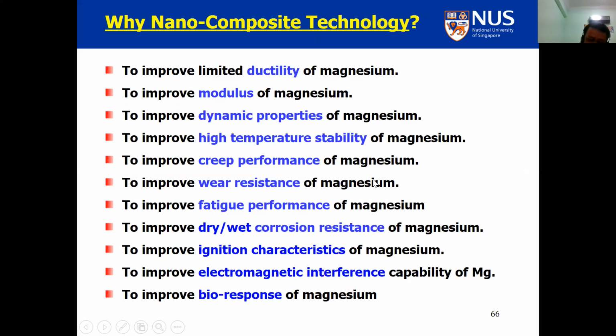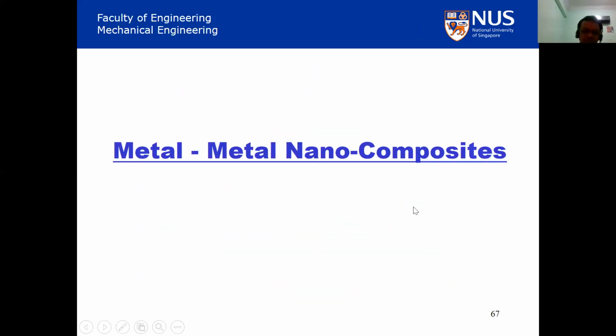With respect to magnesium, which is a hexagonal close-packed material, you can improve the ductility of magnesium by putting in nanoparticles. You can improve the modulus, you can improve the dynamic properties, high temperature stability, creep properties, wear properties, fatigue properties, dry and wet corrosion properties, ignition characteristics, electromagnetic interference, and the bioresponse. So just by putting nanoparticles in a small amount, you can achieve all these different properties.